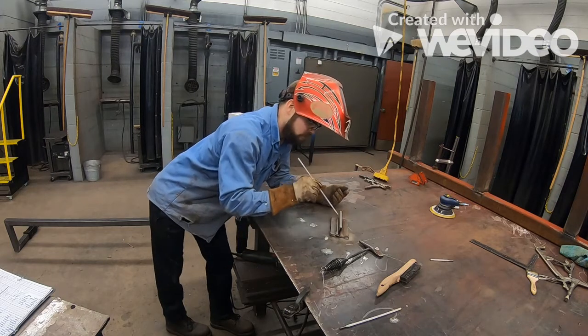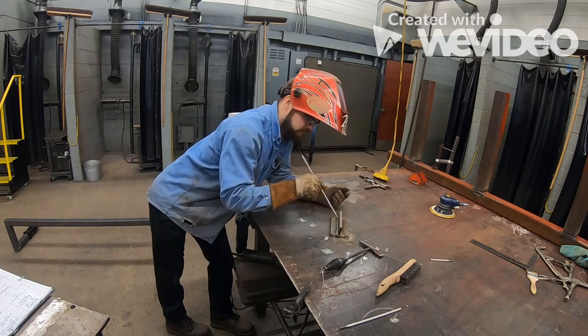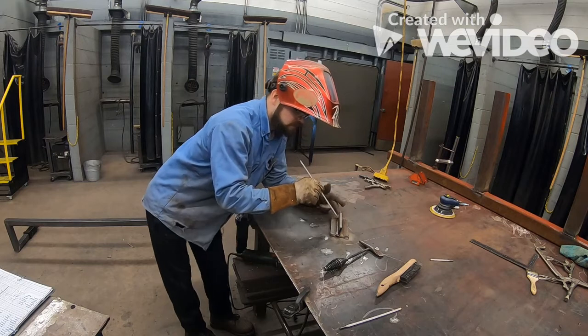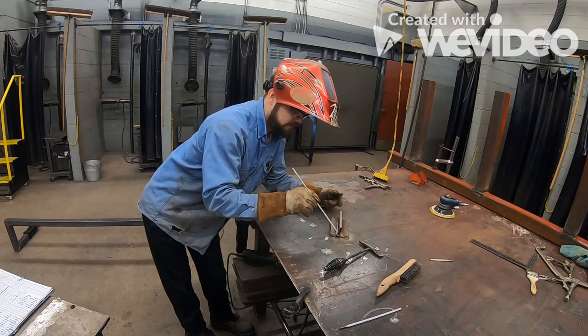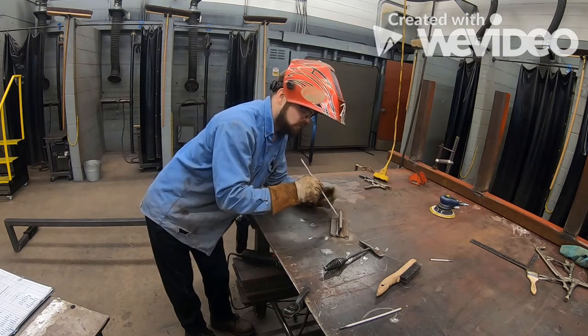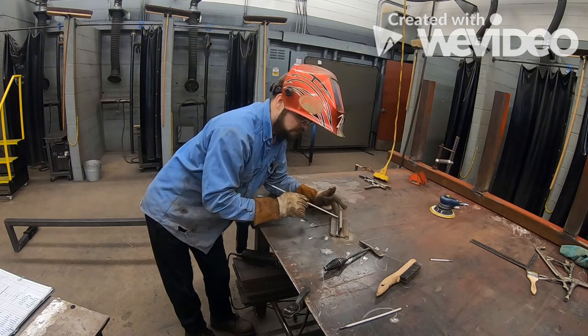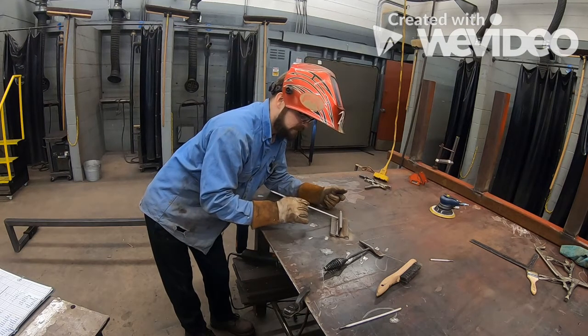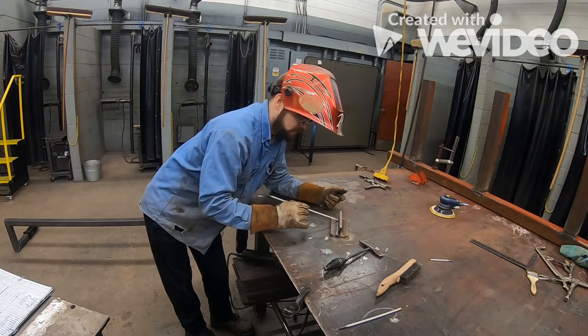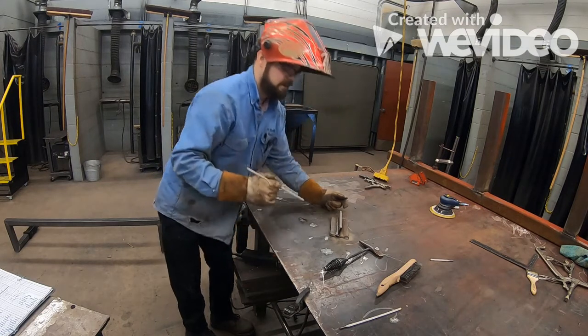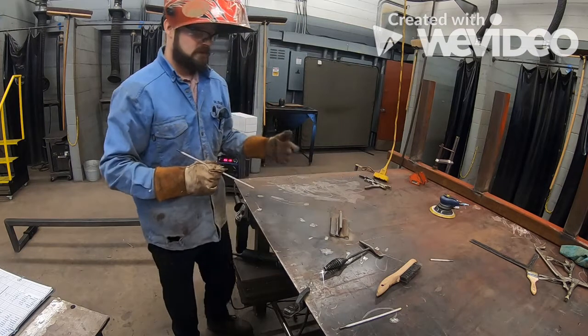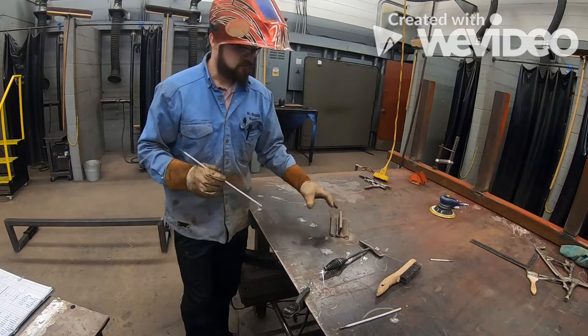Now if you weld this third pass still at a 45, what's going to happen is you're going to get a lot of undercut on the top of this weld because you have the wrong rod angle. That's why we need to drop this down to a 30-degree angle or a 70-degree angle. Okay, weld right across here. Now, remember we can go a little bit faster because it's not our initial root pass.